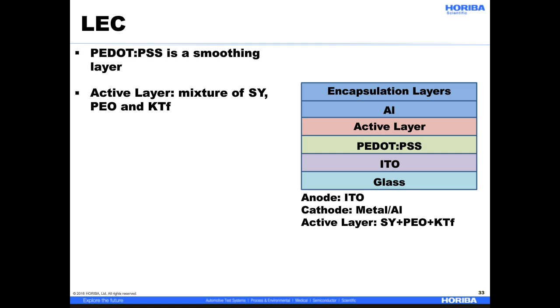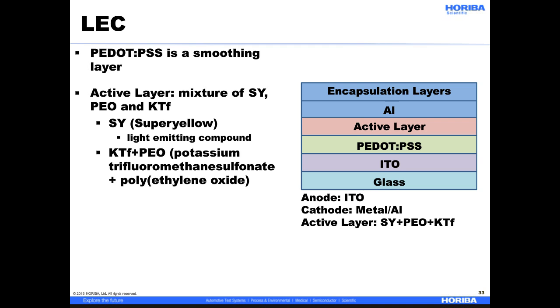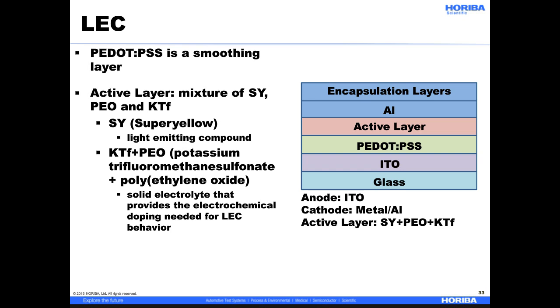is a mixture of super yellow, PEO, and KTF. Super yellow is a light-emitting compound, and KTF plus PEO, which is potassium trifluoromethane sulfonate and polyethylene oxide, is an electrolyte which provides the electrochemical doping needed for the LEC behavior. I forgot to mention the PEDOT-PSS layer is a smoothing layer, and finally we have the encapsulation layer on top, which is resin and glass.